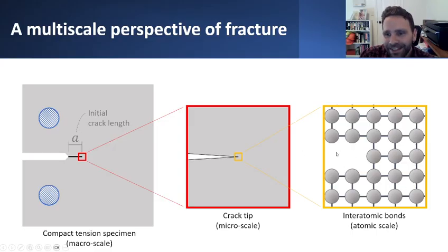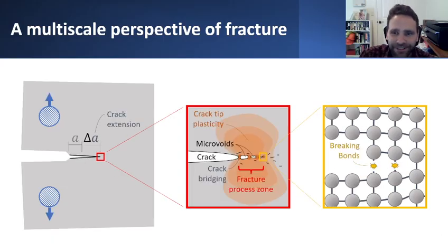And the crack tip is really indicated by just the lack of atomic bonds between rows of atoms. So really, the mechanisms of fracture across these different scales manifest in slightly different observable behaviors. At the scale of the whole specimen, we'll see that this crack, which had an initial length A, has grown by some finite amount, delta A. And we call that, at least at this macroscopic scale, crack extension or crack growth.